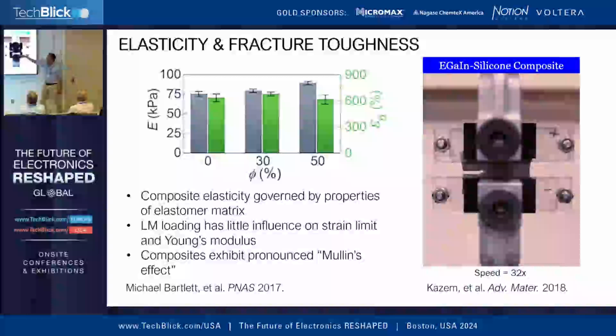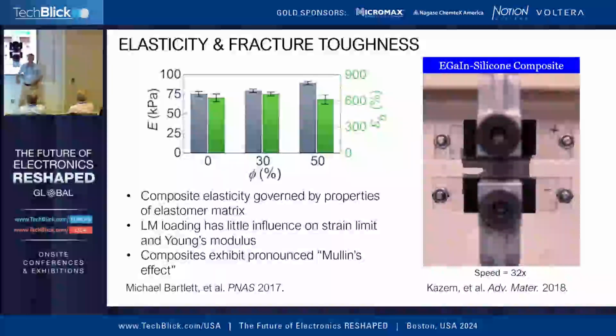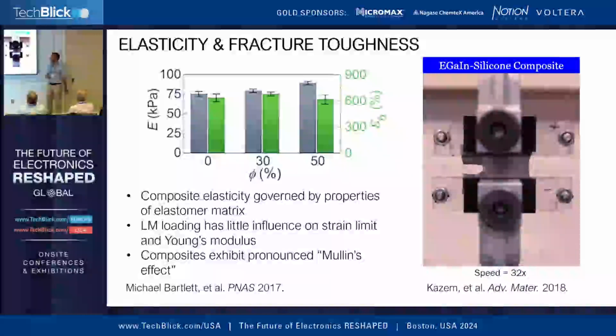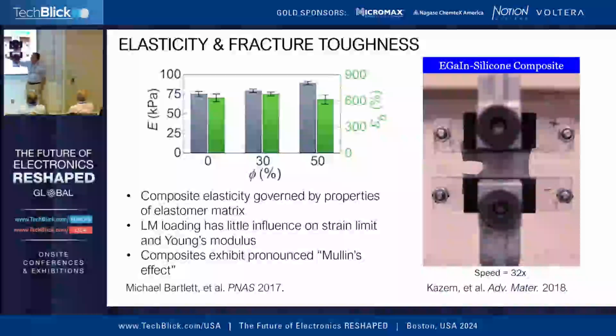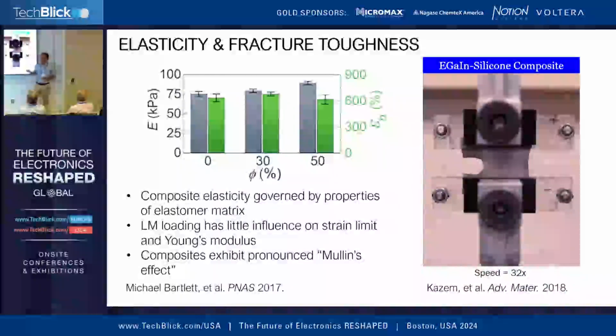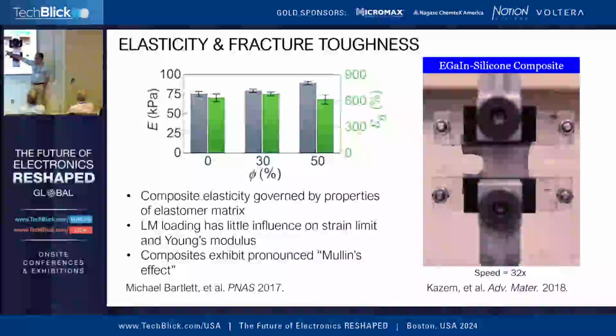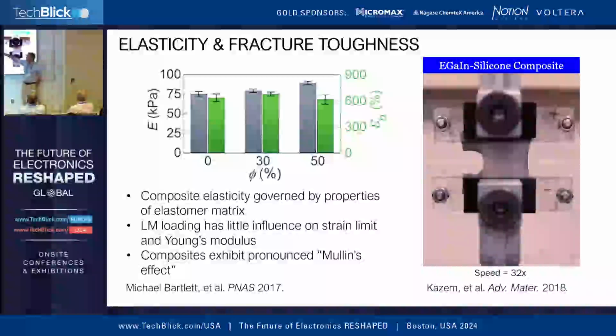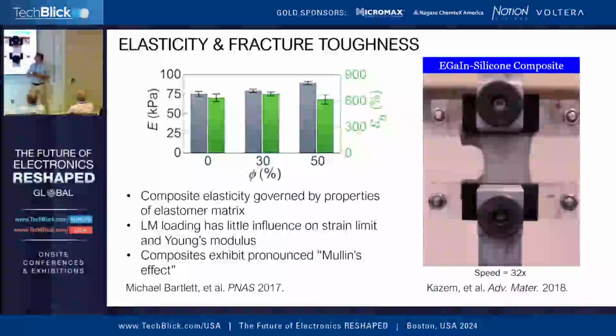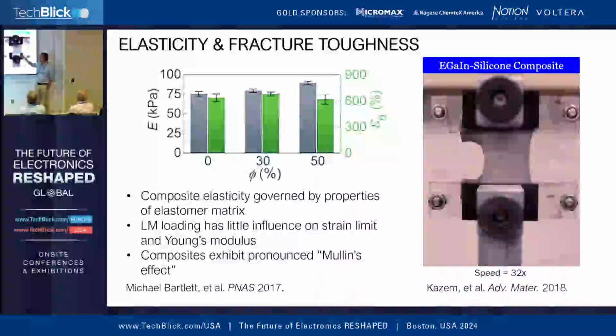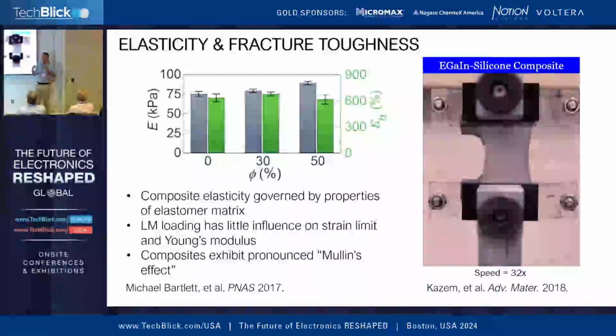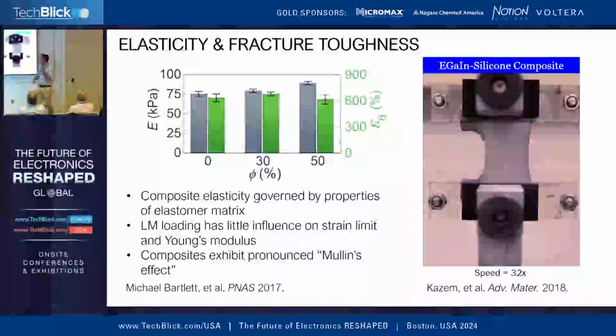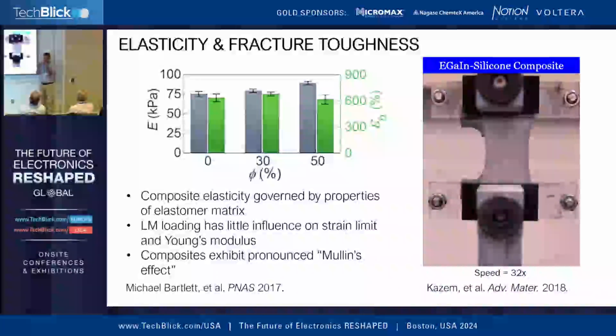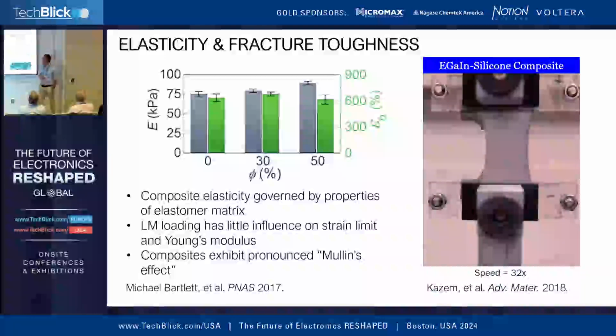As you can see here, even at 50% by volume of liquid metal, so very high concentrations, we don't really alter the mechanical properties of the rubber. In the case of silicone, it still stays soft, with Young's modulus below 100 kilopascals. It still remains stretchable, with strain at break beyond 600% strain. And it has very high fracture toughness. So adding liquid metal actually enhances the durability and the tear resistance of the rubber on account of those microscale droplets and the heterogeneity that comes with that.